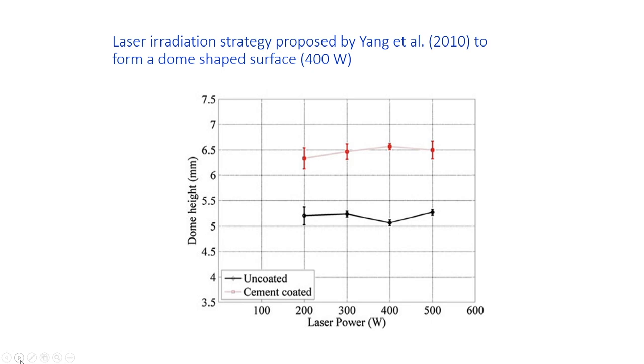Here you can notice the dome height for the cement coated sheet was around 6.5 mm in comparison with the uncoated sheet, which was around 5 mm. So, 5 mm to 6.5 mm is the enhancement for about 400 watt. So, there is a considerable enhancement in the dome height when we apply the cement coating.